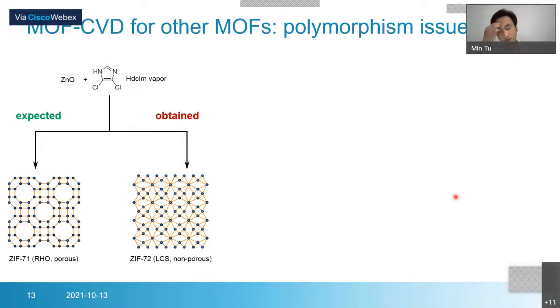Then when we wanted to introduce this technique to other MOFs, we met a problem, the so-called polymorphism issue. Taking one example, here we have zinc oxide. We want to react it with dichloroimidazole, and we expect to have ZIF-71. It has an rho topology and a highly porous structure, with a pore size bigger than ZIF-8. This is what we expect. But when we do the reaction, we get ZIF-72, which is a non-porous dense structure.